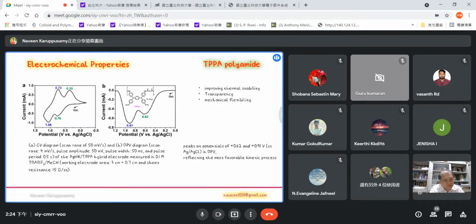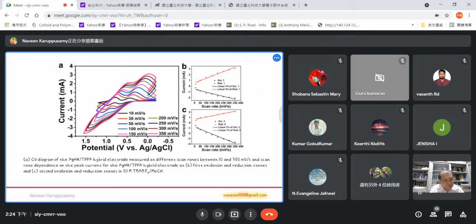flexibility of the silver nanowire, which reflects the most favorable kinetic process. These are different scan rates, used to know the electron transfer kinetics. After increasing the scan rate from 10 millivolt per second to 350 millivolt per second, the cathodic and anodic peak currents linearly increased, which suggests the electron transfer process is a diffusion controlled process.